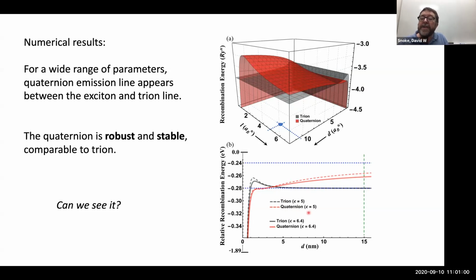And you can see that it's a very stable system. We don't have to get precisely the right D or precisely the right L in order to have the quaternion be stable. It actually then, as I'll show you in the experimental data in a minute, the ordering of the lines, where the quaternion sits, and the actual energies turn out to come out in agreement with the experiment.